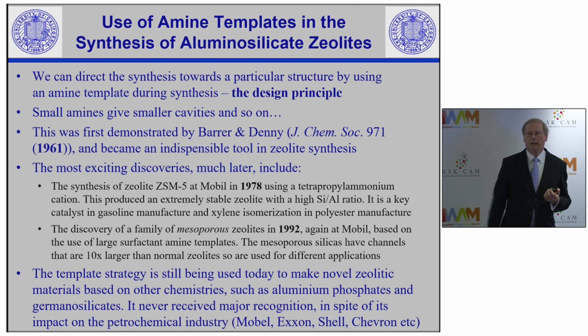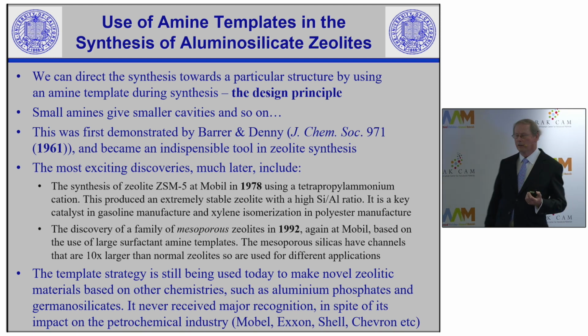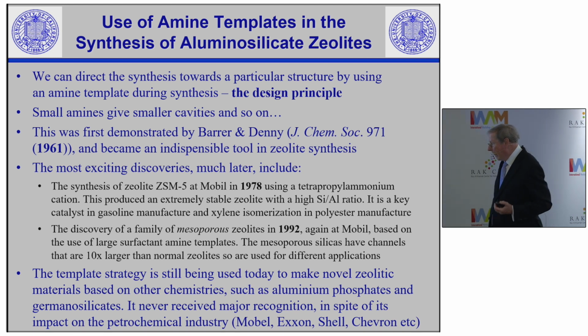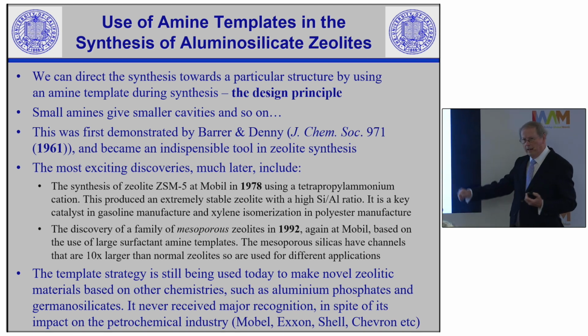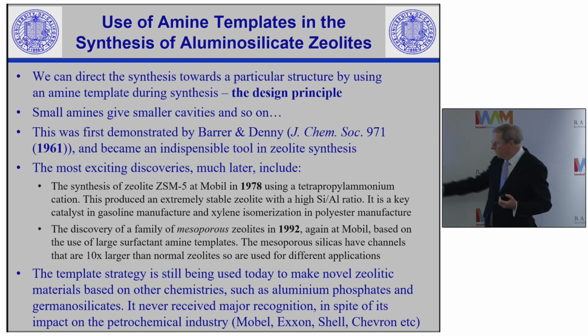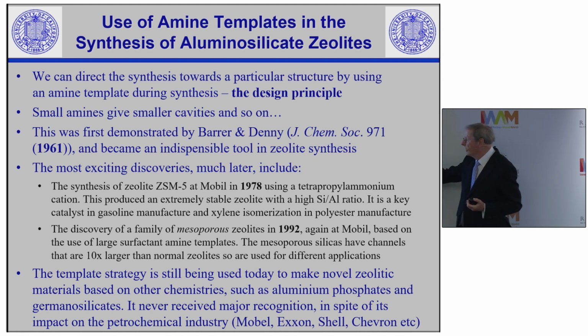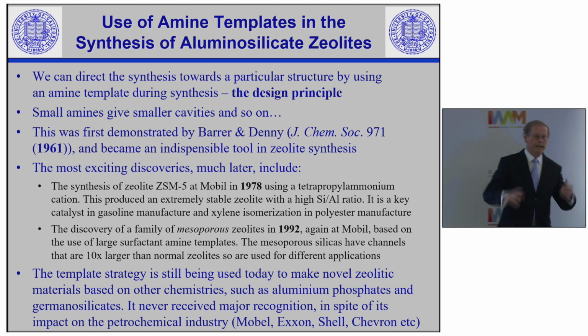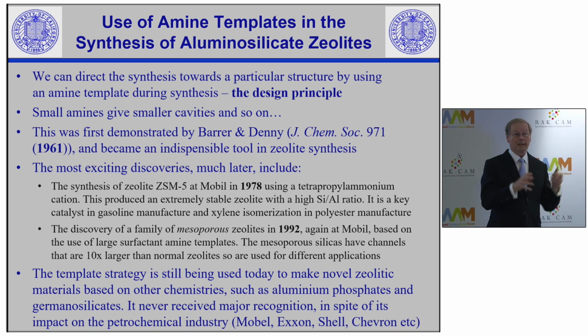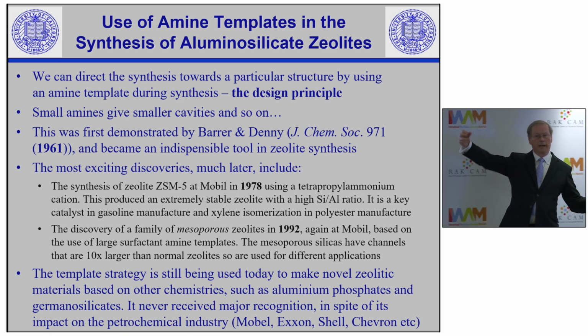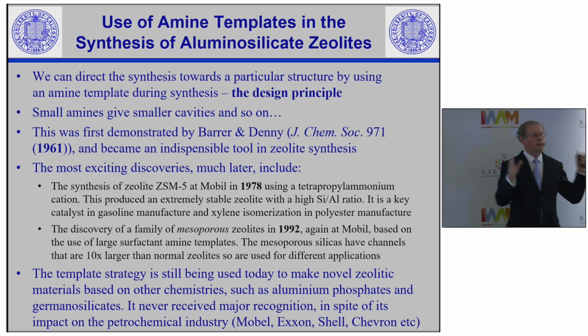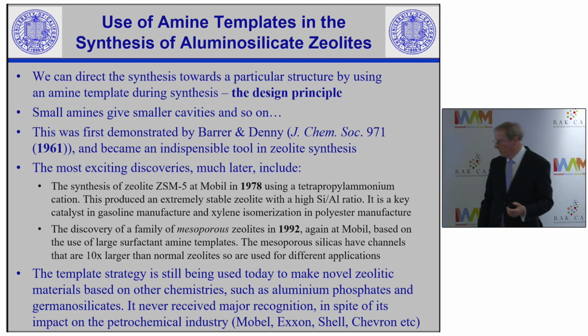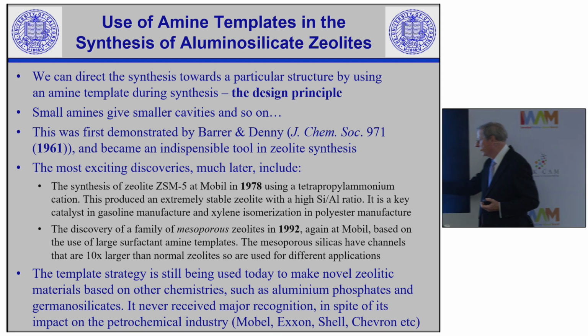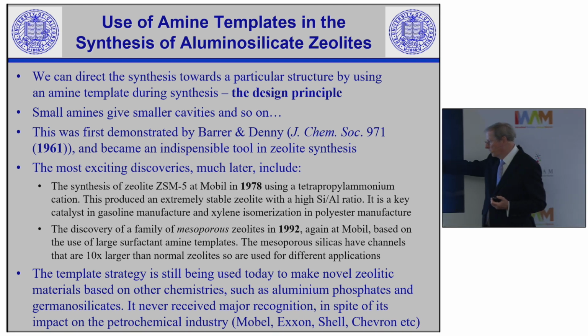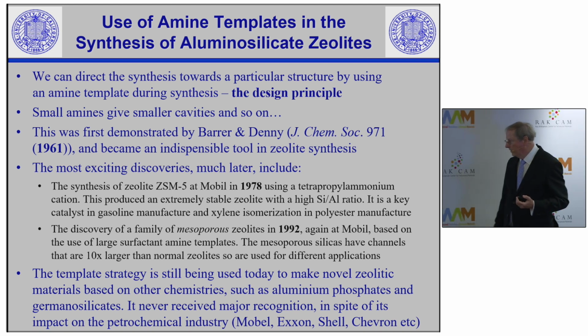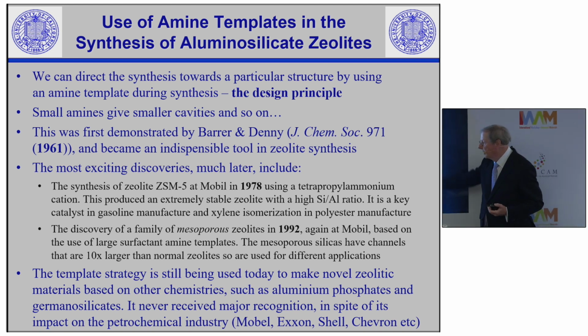And Natalie is an expert in this area, and so I consulted her about this. The other really exciting and somewhat different application of this design principle was to use a really big amine cation, like a surfactant cation, with long chains and so on. And if you do that, you get huge cavities, not just molecular size, they're very large cavities. These are called mesoporous silicas, and this was discovered at Mobil, as was the ZSM-5, this in 1978, this in 1992.